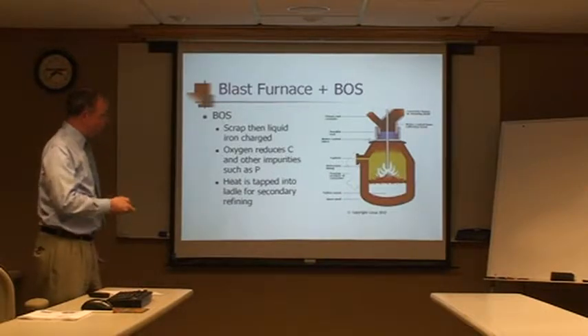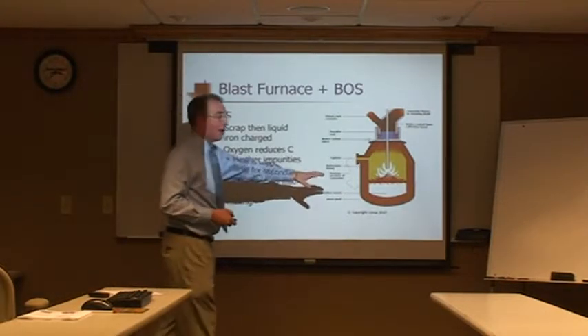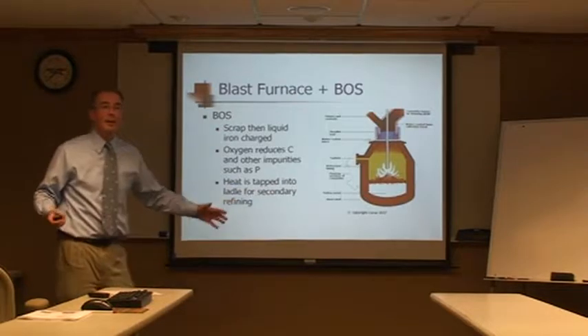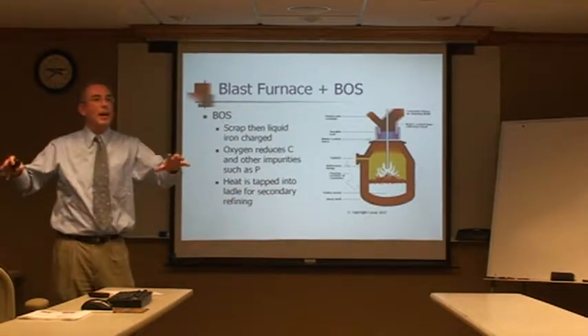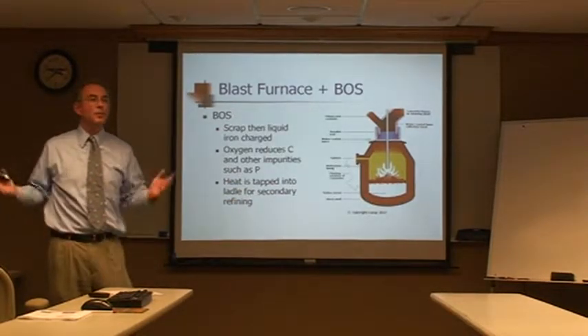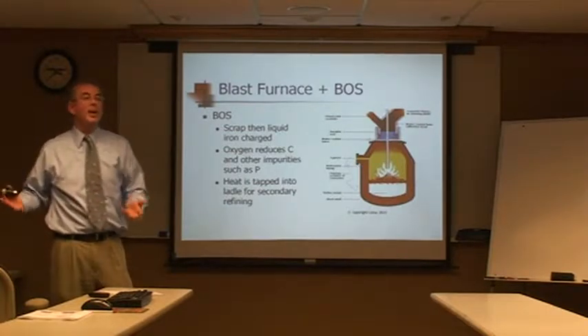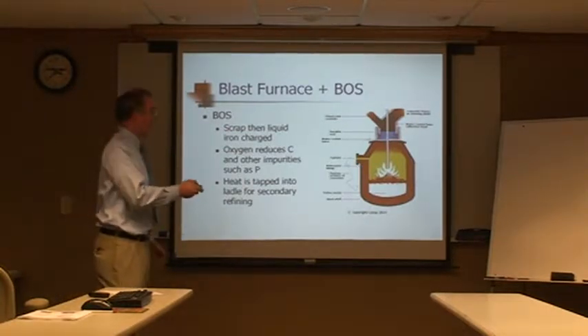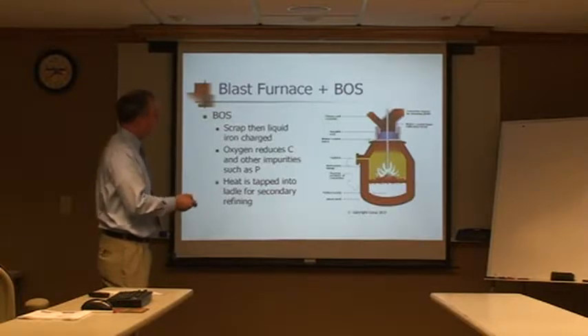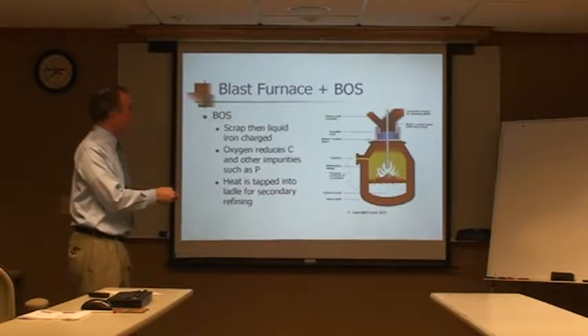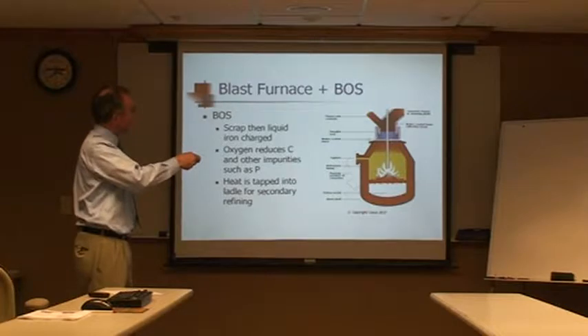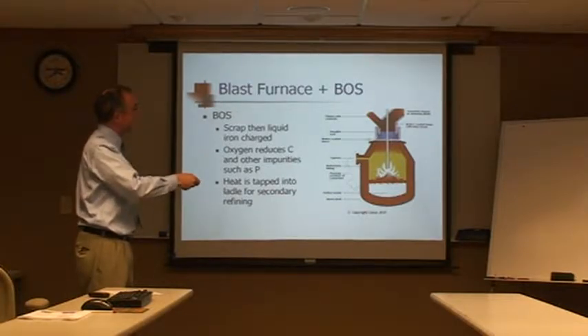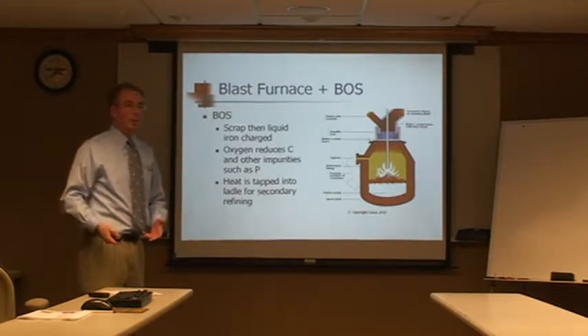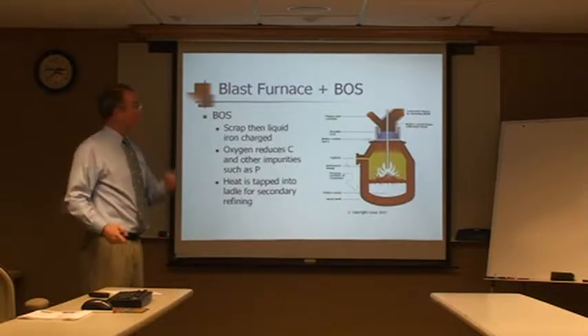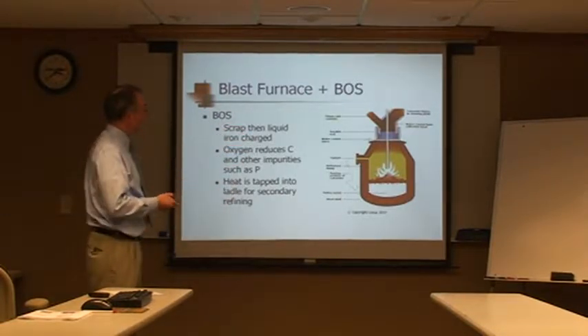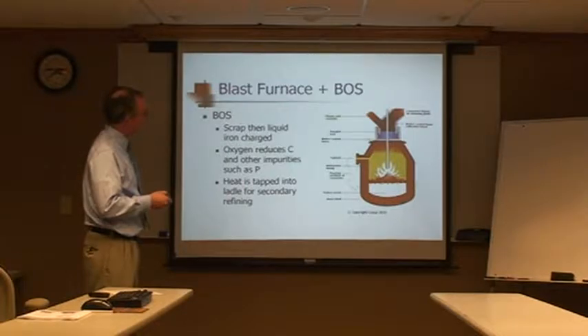So what we're going to do is put some scrap in here. Again, if you're in a steel plant, a flat roll plant, you have lots of scrap lying around, so one of the things you want to be able to do is recycle that, not for free, but take that scrap, charge it back into your vessel, and then again pour the liquid metal into here. Here's this vessel, and then coming down here is a lance. This lance blows oxygen, reduces the carbon that's in the iron, and then once that blow is done, the furnace tilts again, and it's tilted sideways.